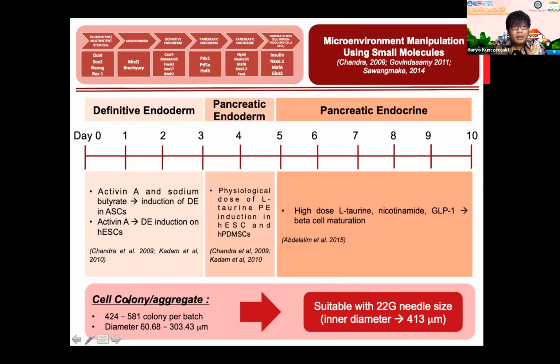As we can see here, for the cell colony aggregates, we can produce 424 until 581 colonies per batch with a diameter ranging from 60 until 300 micrometers. So that's why the 22G needle size is the most suitable, because the inner diameter of the 22G needle is 413. Why do we have to choose the bigger inner diameter here? Because we don't want to break the colonies that we already produced.